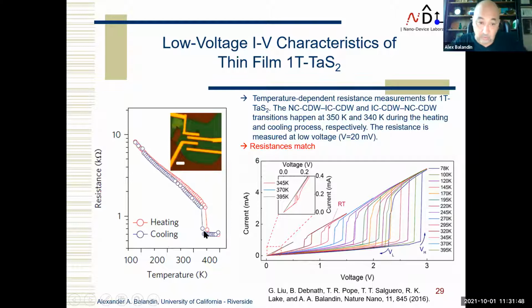And we proved directly that this is indeed this transition. In one case, we measure this resistance as a function of temperature. The scale here is a little bit offset, so this happens at 350. We can check what the resistance is here and here, and then we measured by applying voltage, and the slope gives resistance. We put those resistances together, and we proved that the resistances match.